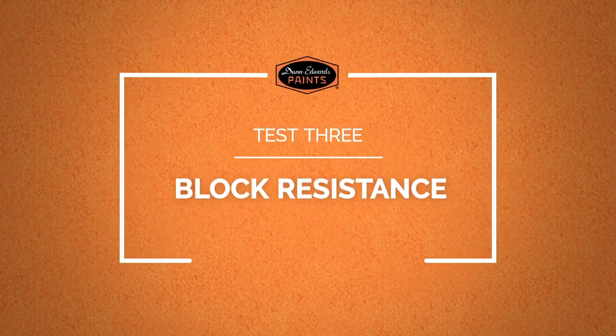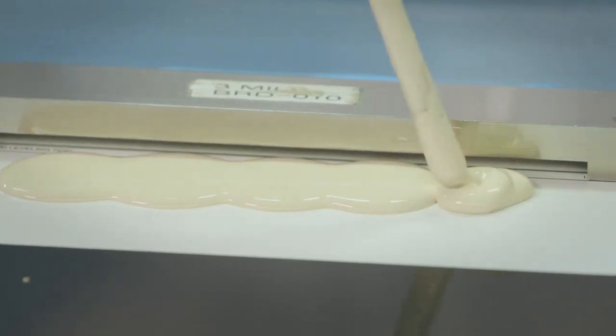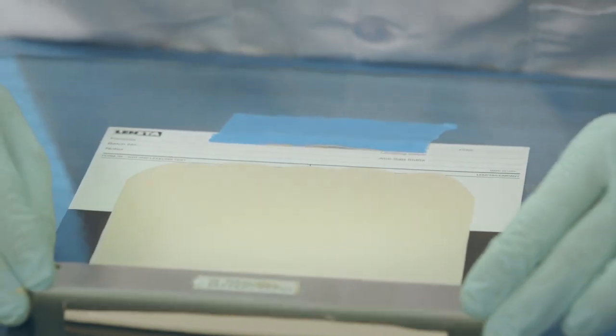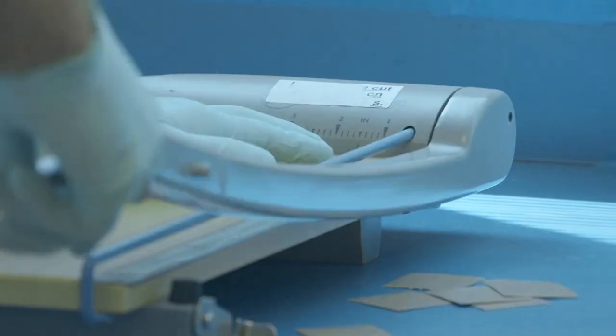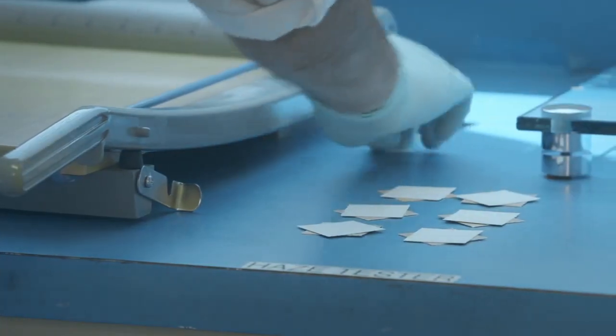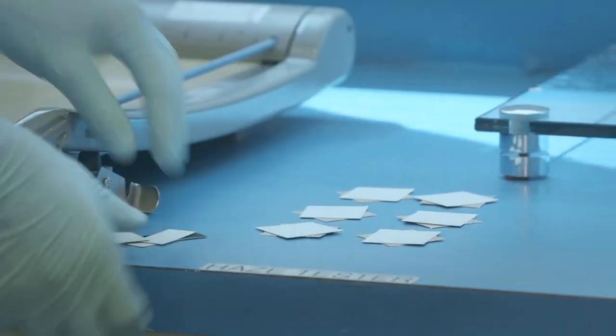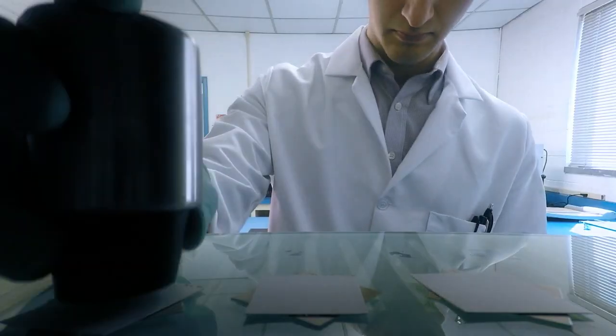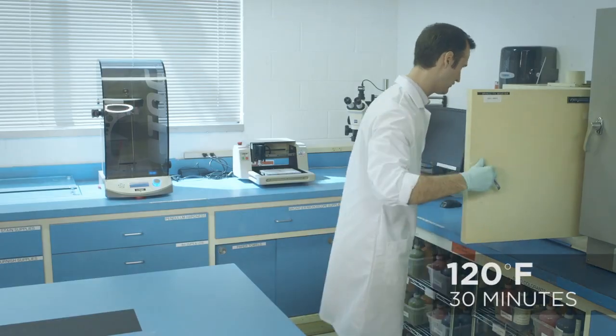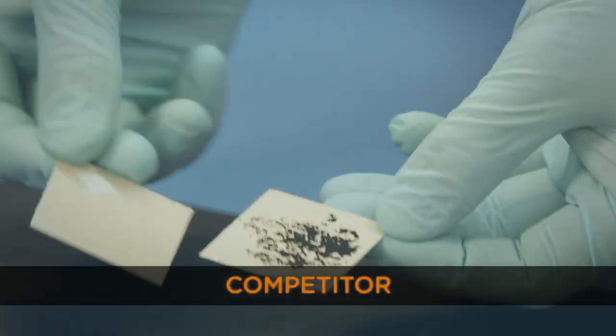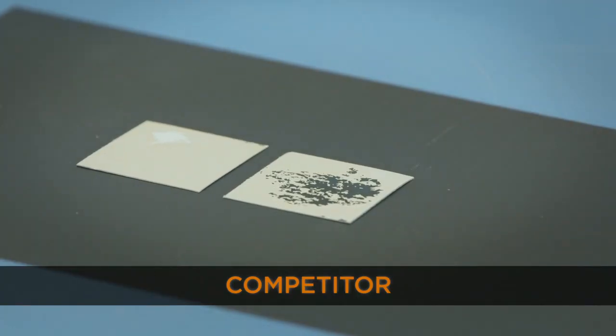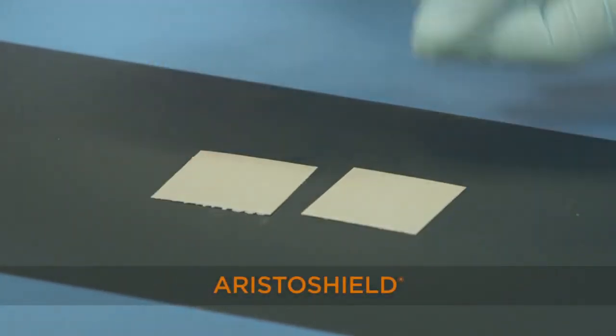Block resistance is essentially where two painted surfaces come together in contact, and it'll have a tendency to stick to itself. We'll do a drawdown of the paint onto a panel, cut it into 1.5 inch squares, place the panels face to face so that the painted surfaces are in contact with each other, put a weight on top so that we have a consistent amount of pressure, and place it in the oven at 120 degrees Fahrenheit. Those panels get removed from the oven, and then we attempt to pull them apart and rate them. In the case of Aristoshield, you'll notice that there's very little tack and there's no paint film removal.